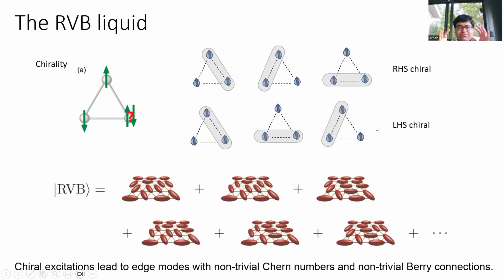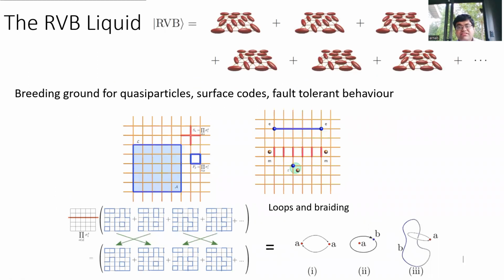So what you can see is that just from a triangle, which is one of the simplest frustrated motifs, you can actually get some very interesting chiral features. You can get many degenerate ground states and many excited states, all from one. And now, if you take this triangle and extrapolate it onto a large lattice, like a large Kagome lattice, then you would get a superposition of several dimer coverings. So your final ground state will be a superposition of several of these dimer coverings, and that's what you will see as your signature of the spin liquid.